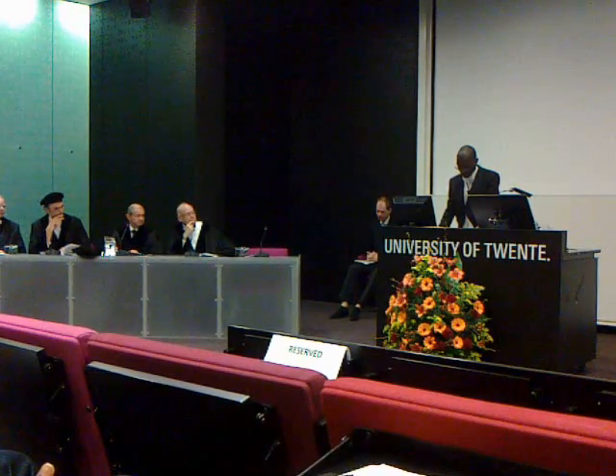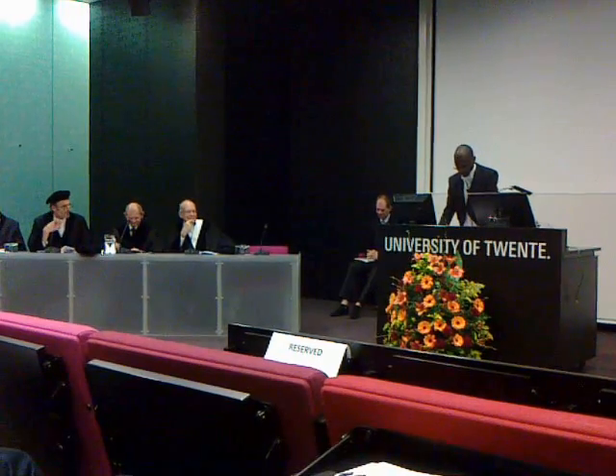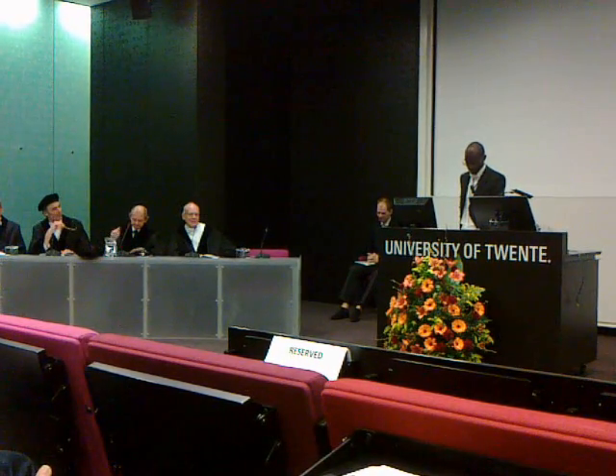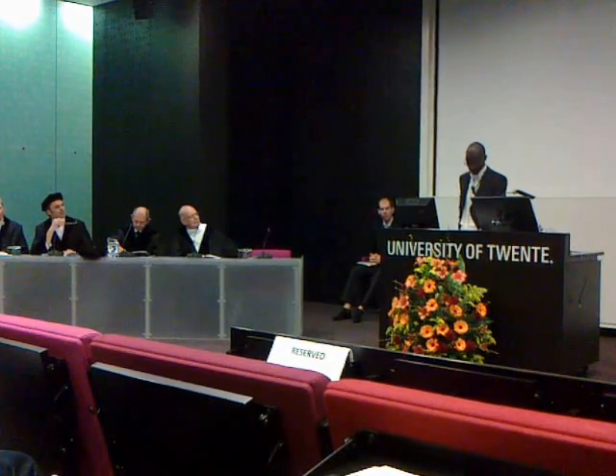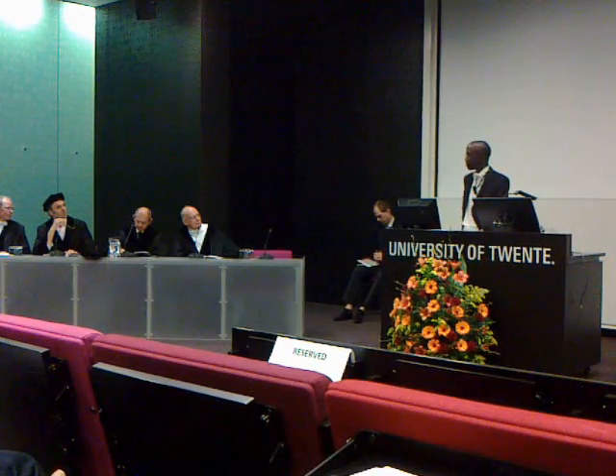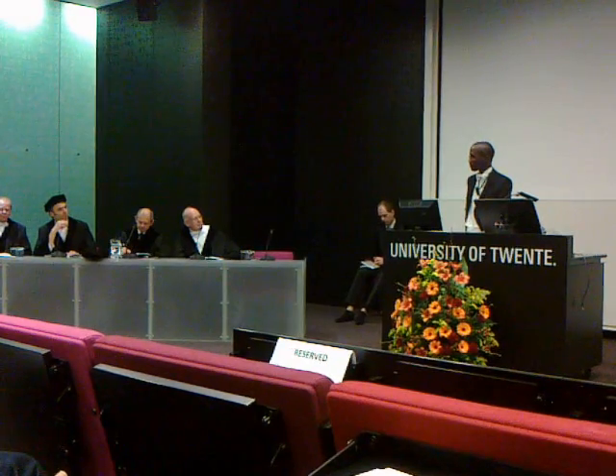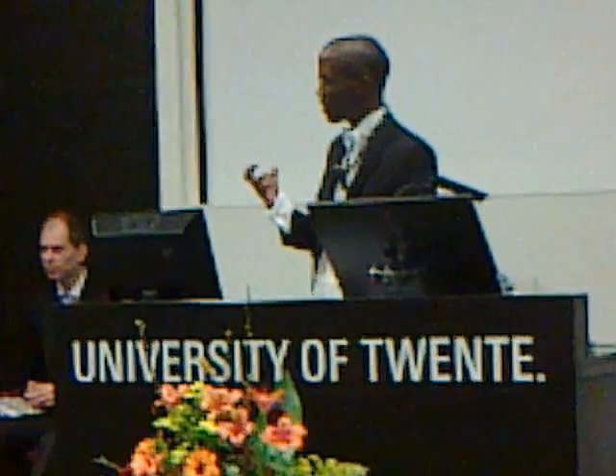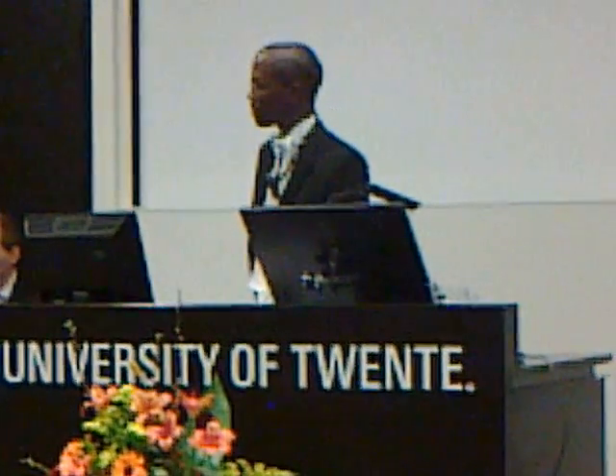No, I think I see it the other way. Okay. Well, please explain. I'm interested. So I just have a tangible example. If you look at the way boron interacts with molybdenum, if you have more of it, you tend to form more of a boron-rich metal plus boron compound intermix. So it really depends on how much material you have. It's about concentration. So if I have less, nothing much will happen. Of course, it will diffuse, but not at the same rate compared to a system with higher concentration. And that's the basis of my thesis.